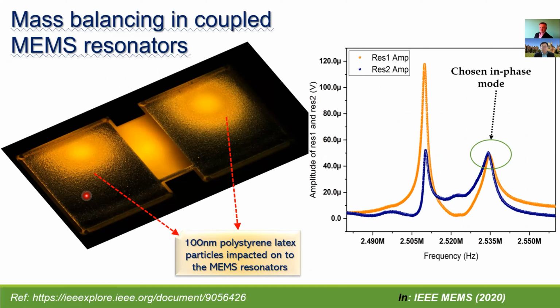So one thing we did, in order to test the lifetime of these sensors, is we initially tried impacting 100 nanometer polystyrene latex particles at higher concentration onto these coupled MEMS resonators for 5 minutes on the first resonator and for the next 5 minutes on the second resonator, to see what would happen in the coupled MEMS resonator system. For observing this response, we chose the in-phase mode of operation because the amplitude ratio starts at 1 for the in-phase mode.